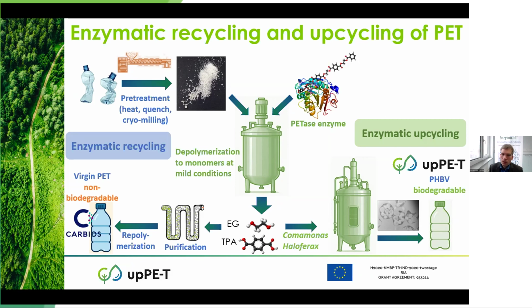Enzymes, the PETases, have got some requirements to degrade plastic. Mainly, it's very important that the PET is amorphous. You have to know there are amorphous and more crystalline forms of PET. You can see that when you look at different types of packaging material. For example, you have more labile fruit packaging, like for strawberries, which is mainly amorphous. And on the other hand, you have more rigid packaging, for example, PET bottles, which are more semi-crystalline. And so in a first step, all of the more crystalline PET has to be amorphized.